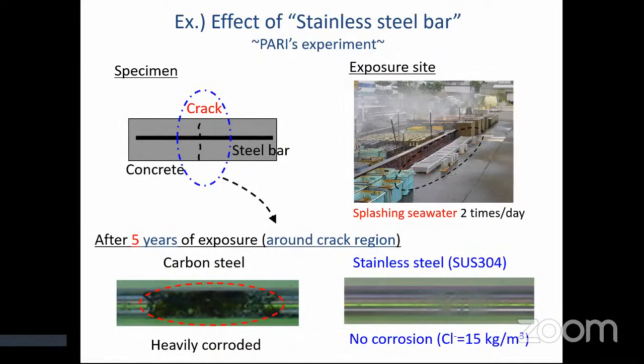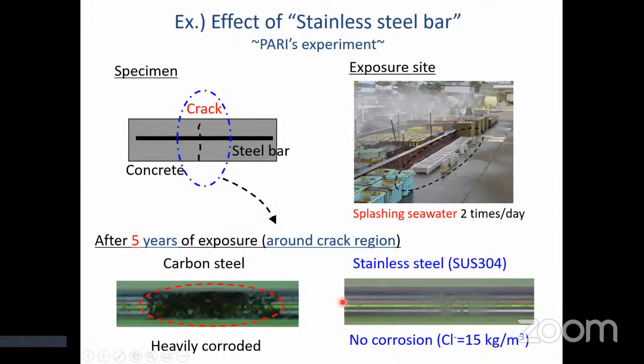Also, this slide shows one example of the effect of stainless steel bar in our experiment. A cracked concrete specimen with steel bars was exposed at an exposure site for 5 years. There is heavy corrosion on the normal carbon steel. On the other hand, there is no corrosion on the stainless steel. These results indicate stainless steel bar has high corrosion resistance.